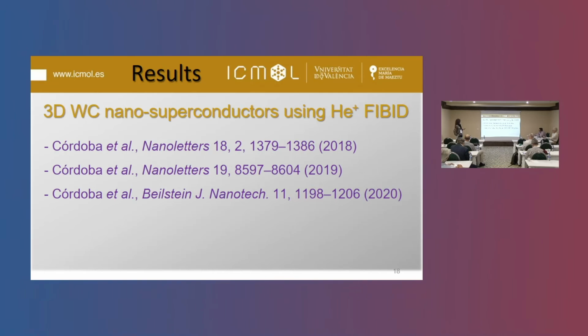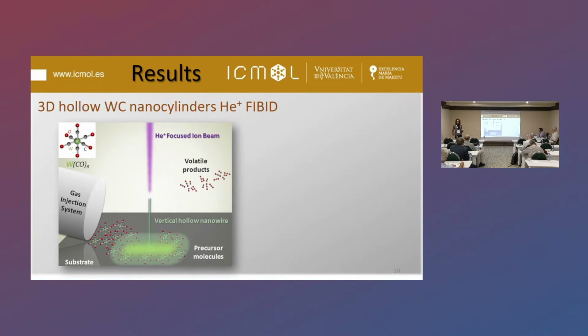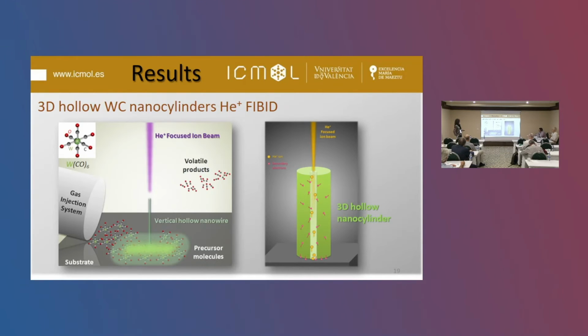So I'm going to summarize some work already reported in different papers regarding 3D superconductors using the helium beam in order to get really small nano-superconductors and devices. And the first example is the fabrication of hollow nanocylinders, and it's a very simple way to do it. There are precursor molecules that adsorb on the substrate, and the helium beam stays at the same position for the deposition time, producing two effects.